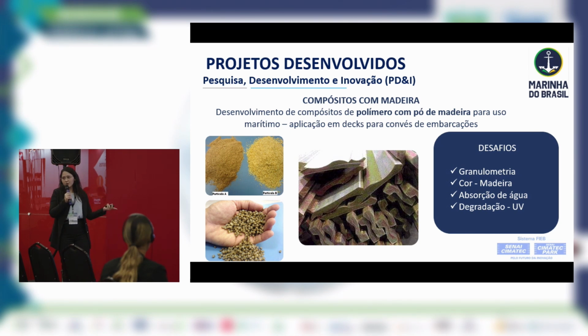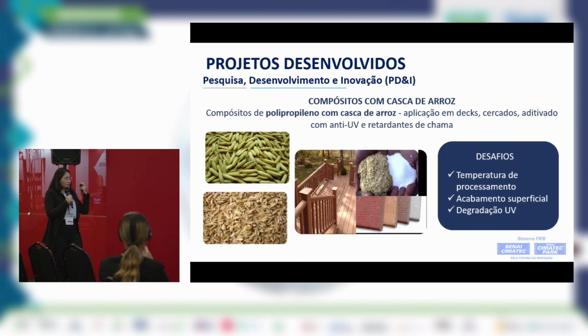The color of the wood may interfere in the final product. So if you want to do this in large scale, the color can be an issue. Depending on what type of wood you use, then you have different colors, and that can be a challenge. Well, we need this to be equivalent. Also, water absorption. We need to properly dry the material before processing it. And application is for the deck, the external deck of vessels. So we have to be concerned with the UV degradation. So we use additives to protect the material against the degradation.